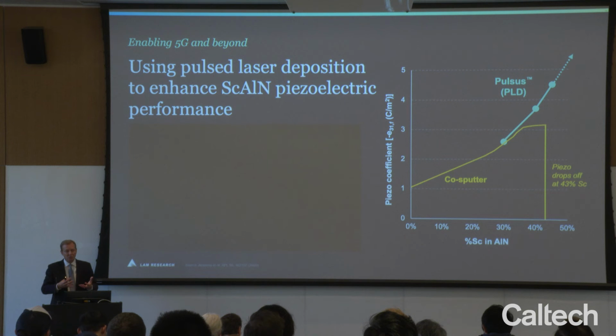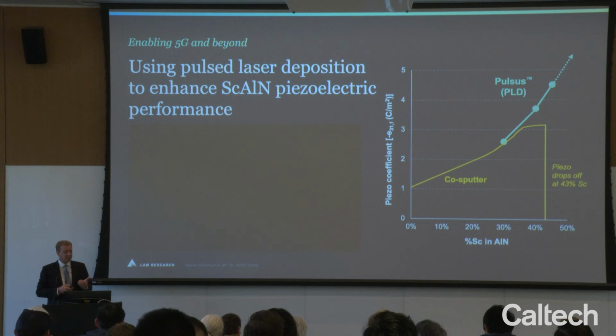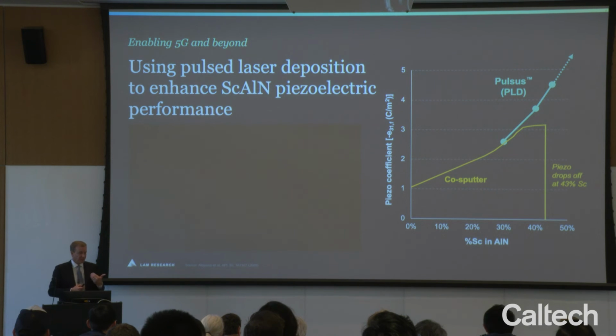Again, as we continue to push the technology, this idea of trying to balance sputtering of two targets doesn't work, and we've now focused our attention to what is called pulse laser deposition, where you have the target actually manufactured with the precise balance and ratio of the species that you want in that target, and we can basically then deliver those to the surface of the wafer. And that's allowed us to push the scandium concentration in these films higher and ultimately end up providing better devices for our customers.